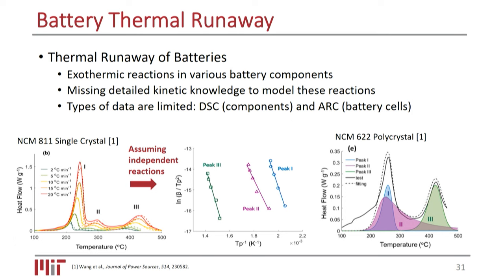If you say, yes, there are three peaks, please fit it to three peaks. And here's a fitting result. You do have the three distinct peaks, but something does not look really right. You can still fit the profile very well. However, your second peak, which is supposed to be a reaction that happens after your first reaction, now happens before the first reaction. So physically, it's not really making sense, but data-wise, it's a good fit, right?